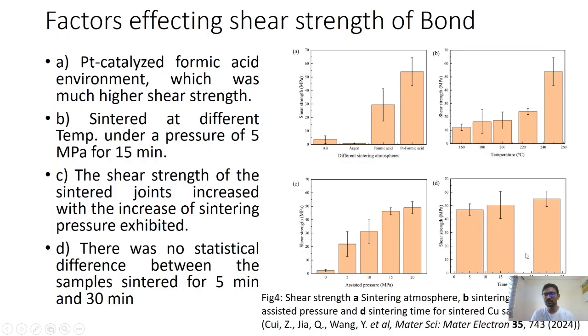In this figure, you can see that if we are doing sintering for 5 minutes, we will get a shear strength of about 45 megapascal, and if we are doing sintering for about 30 minutes, we will get 52 or 53 megapascals. So there is not much difference between the shear strength. So you can see we can do rapid sintering at low temperatures for copper-copper bond. This was all about when we are using nanoparticles.